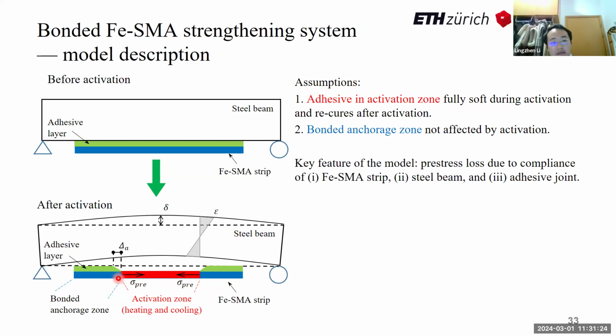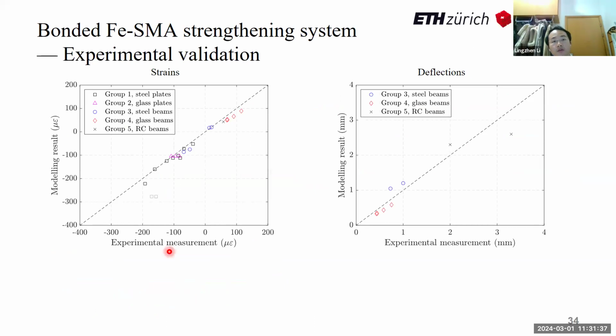Further, in the analysis, I considered the generated prestress, the shear deformation of the adhesive bond, and the compressive bending deformation of the substrate. In the end, the model could successfully predict the strain of the substrate caused by the generated prestress, and also the deflection of the substrate. These two figures show the modeling results versus experimental measurement.